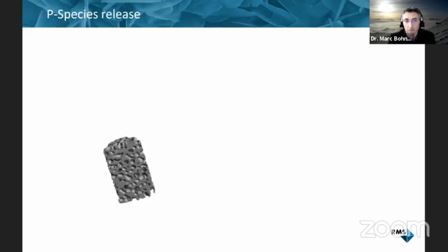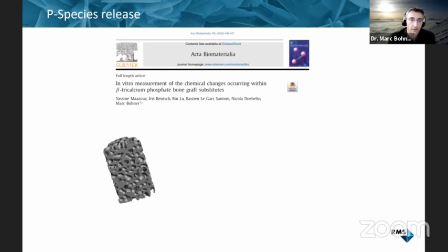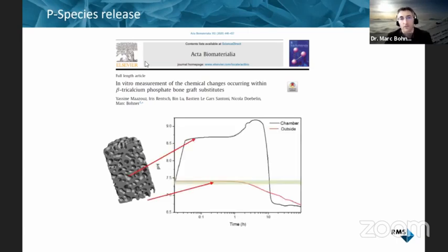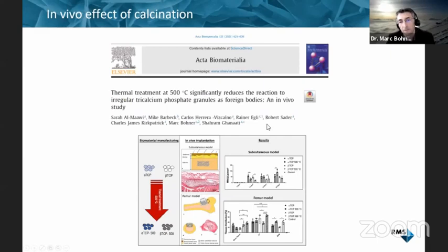Then one issue we may have is that I mentioned we have evaporation of phosphorus species, and if you look at the scaffold like this, you can maybe polish the outside, but there's no way you can polish the inside. And since we form all the time this calcium oxide, we generate alkaline conditions inside the scaffold. And actually Yassine Mazouz showed in a similar system that we can have a fairly alkaline pH occurring on the inside of a scaffold compared to the outside.